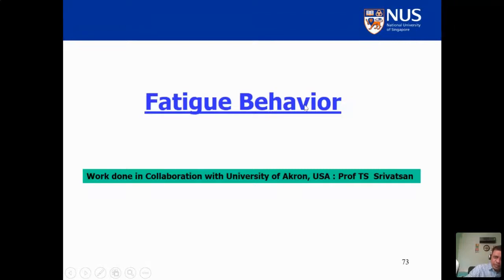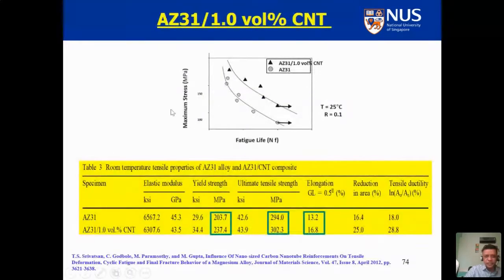Now, one of the ways in which the material fails when they are in service is under cyclic loading, which is commonly called fatigue. We did some work in collaboration with Professor Srivatsan at the University of Akron. He works on fatigue. And you see that when you take a commercial alloy, AZ31, and put just 1% of carbon nanotube, for a given stress level, the number of cycles to failure is much higher. This is besides the improvement in the tensile properties, which has been established in general for many, many nanocomposite systems.